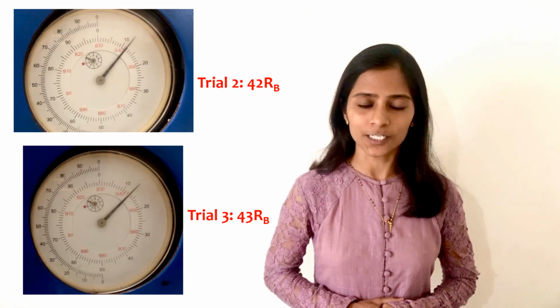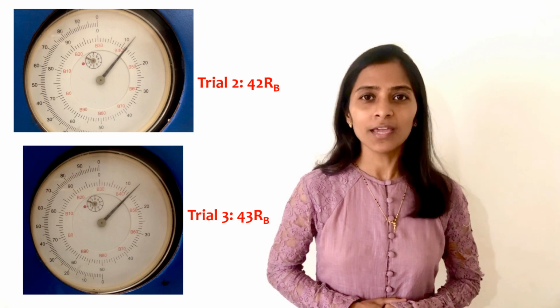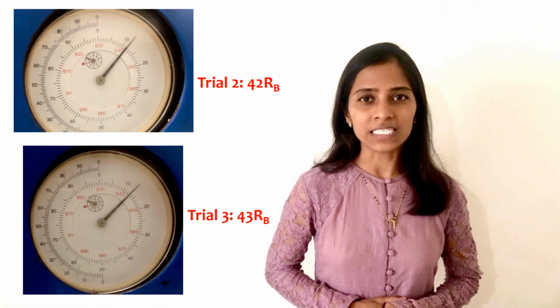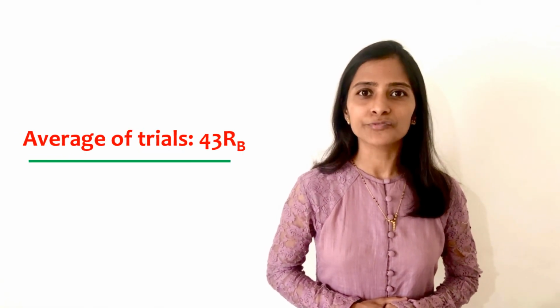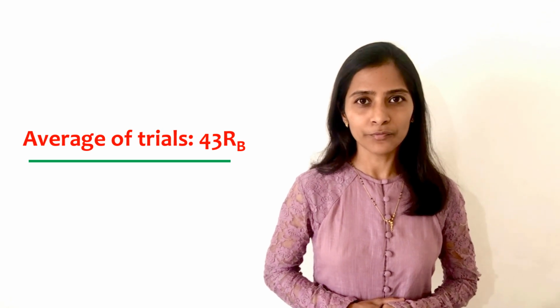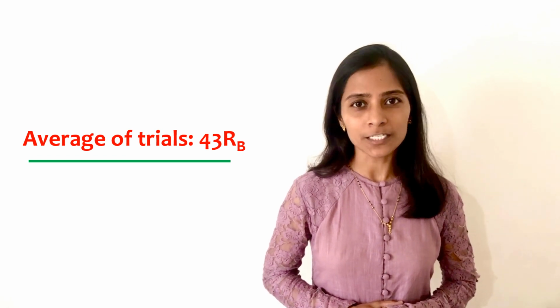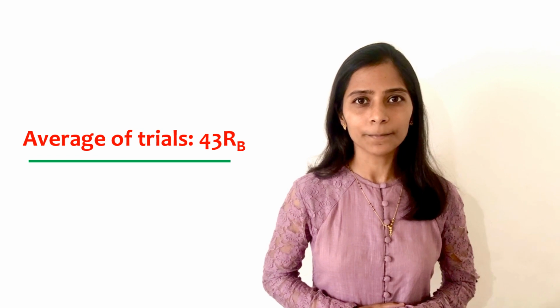According to the second and third trial, the hardness of the test specimen is 42 RB and 43 RB. Thus, the average of all 3 trials is 43 RB. Therefore, the hardness of the aluminum test specimen is 43 RB. In the Rockwell hardness tester, the dial is calibrated in an inverse fashion, because of which the hardness number is directly proportional to the actual hardness of the material.